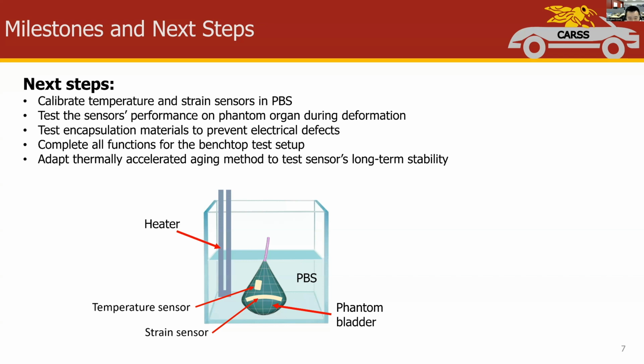Lastly, we'll finish up the benchtop test setup, completing all functions, and as you can see in this illustration, we will use a large glass tank with solution to hold liquid, and use a heater to control the temperature. We will immerse the organ with sensors in this temperature-controlled liquid environment, and then test both encapsulated sensors in the thermally accelerated aging method to make sure both sensors can have long-term functionality.